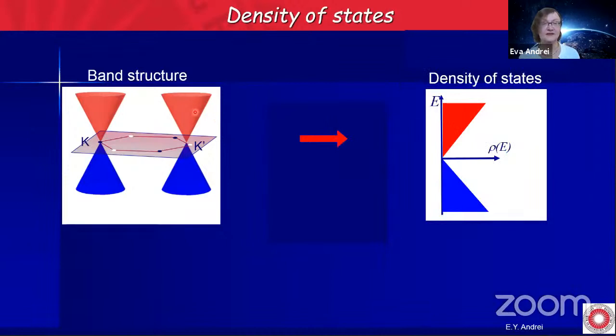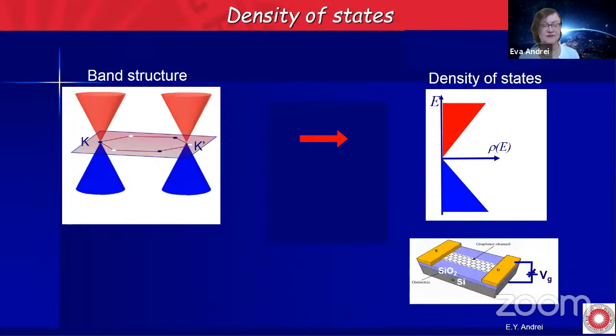So as a result of this linear dispersion, the density of states, which is the number of states per unit energy in graphene, is linear in energy and vanishes exactly at the Dirac point. Now, this is quite remarkable because it enables us experimentally to do the following experiment. So here, this is a typical device that we can make out of graphene. It's called a field effect transistor.